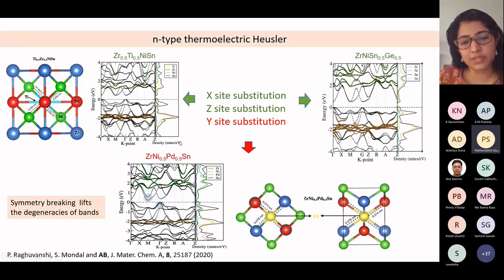However, if you are doing a substitution at the Y site, it's not very good, and it breaks the entire symmetry of the lattice. And that is the reason that all the literature until now in thermoelectrics focuses on either X site substitution or Z site substitution of Heusler materials, but not Y site substitution, because it kills the electronic structure. So it kills the degeneracy in the electronic structure.